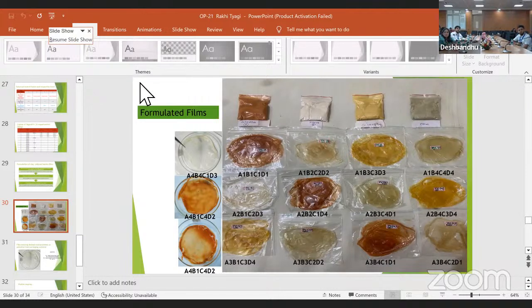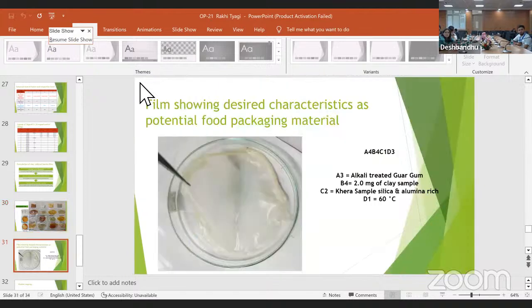Till now I have formulated 12 films, and this film is A4, B4, C1, D3. A stands for the alkali treated guar gum, B stands for 2.0 milligram of clay sample, C indicates the sample which was silica and alumina rich, and D is the formulation temperature. This film showed promising properties which can be further explored for food packaging application.